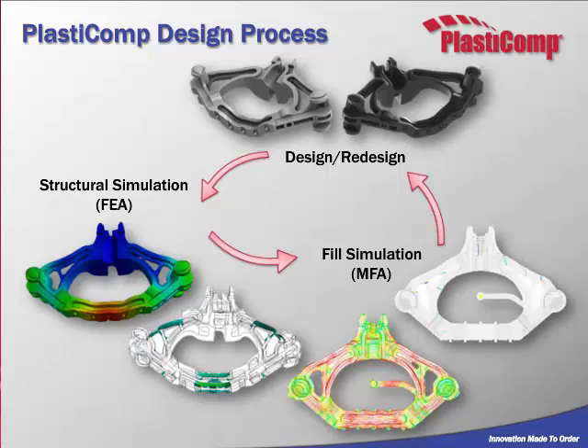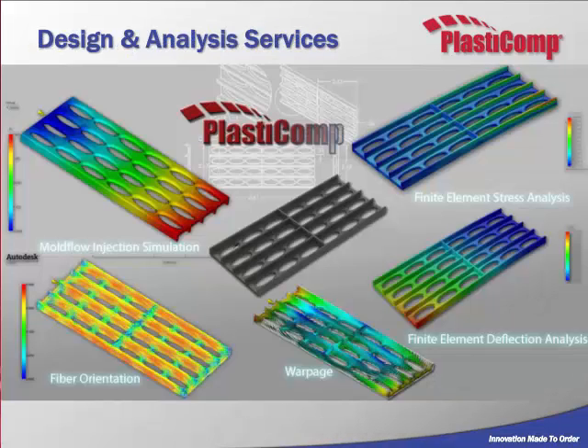We typically make a PowerPoint to help explain what's happening in your part, and to walk you through how everything works from a moldability perspective and a long fiber perspective. Then after we find these things out, we redesign to fight those stresses, adding material where you need it while removing material where you don't. So you can end up with even more than 50% weight reduction. That'll keep you able to compete with your field, just to give you an edge over your competitors.